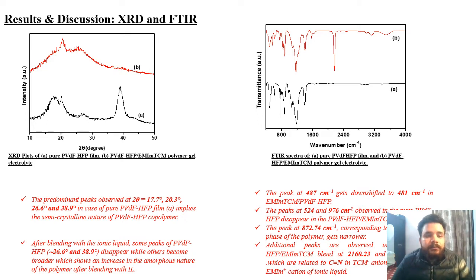In case of ionic liquid doped polymer film, you can see that the two peaks at 26.6 degree and 38.9 degree disappear when ionic liquid is doped inside it, and the other peaks are broadened, which shows that the crystallinity of the PVDF-HFP copolymer decreases when we add ionic liquid in it.